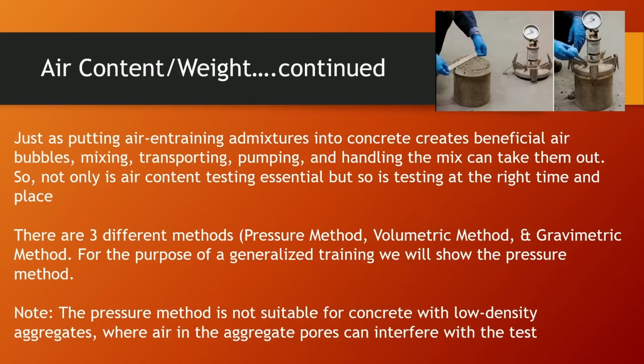Again, there are 3 different methods. There's going to be a pressure method, a volumetric method, and a gravimetric method. For the purpose of a generalized training, we're going to show you the pressure method. I'm going to say 8 out of 10 times when that third party shows up, they're going to show up with an air pot like shown in the top right, and they are going to be doing the pressure method. The pressure method is not suitable for concrete with low density aggregates where air in the aggregate pores can interfere with the test.